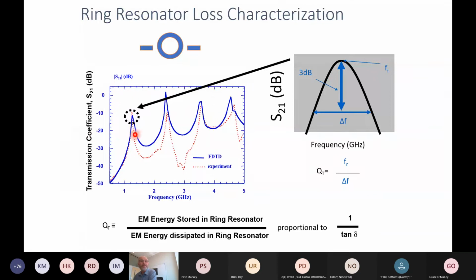So looking a little more deeply at this fundamental mode, again, looking at the transmission coefficient, the amount of power making it through the ring resonator structure as a function of frequency, we can actually get this Q value by looking at where the resonant frequency is, FR, and then this peak width. And by this relationship with the peak width, so the wider the peak, the larger the delta F, the lower the Q. And we can get some measurement then of the Q of the device by measuring that peak resonant frequency and the width. And that Q is basically related to the energy stored over the energy dissipated within any resonant device.